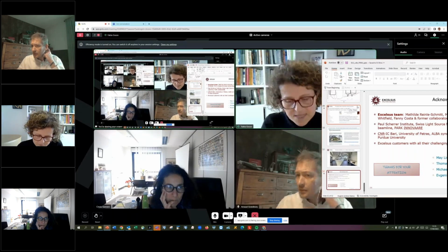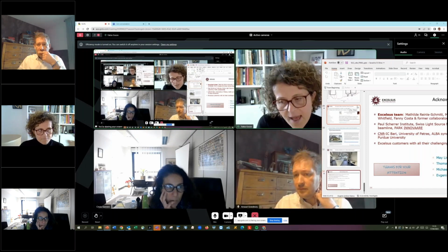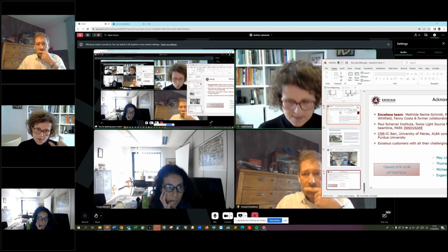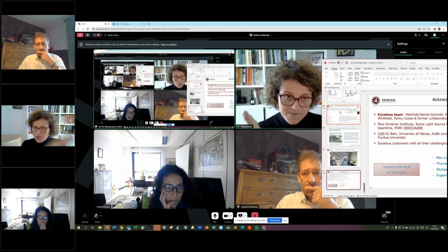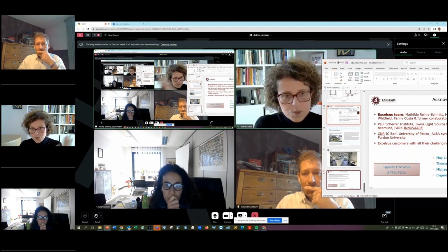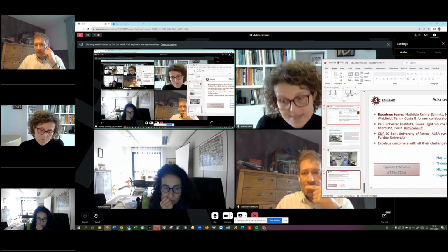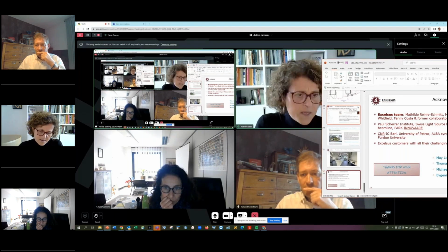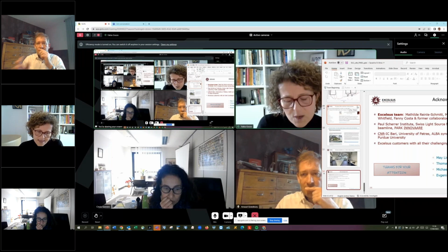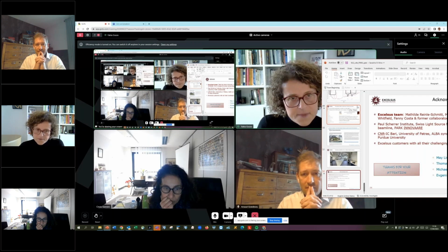The disadvantage is that by underfilling the capillary, you have a virtually smaller capillary size only at very low angles. As soon as you reach 90 degrees, you see the entire projection of the capillary. But for these kinds of materials, and in particular for indexation, this is a huge advantage, because essentially you get very, very sharp peaks at low angle. This made a huge difference.